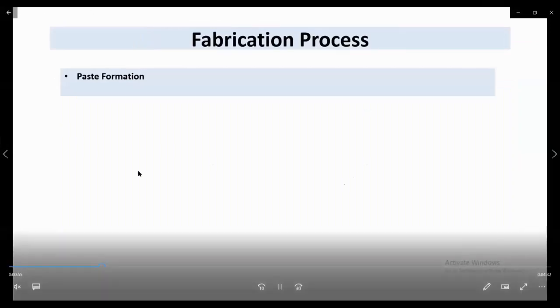For the fabrication process here, the paste was formed. For this paste formation, TiO2 and ethanol were ground into a smooth paste and 3 drops of Triton X100 were added to it. The dye extraction was done for the beetroot, pomegranate and the blackberry. So, the main part is how one can prepare the electrode.